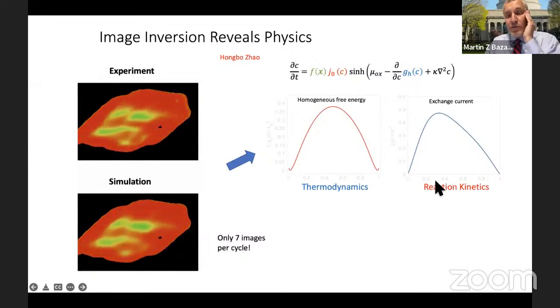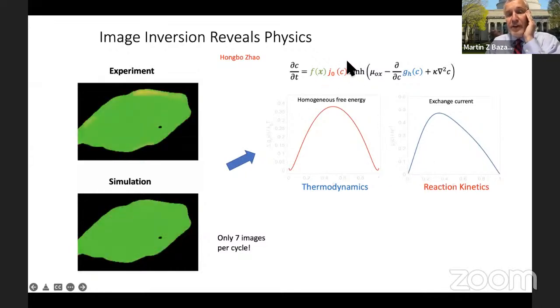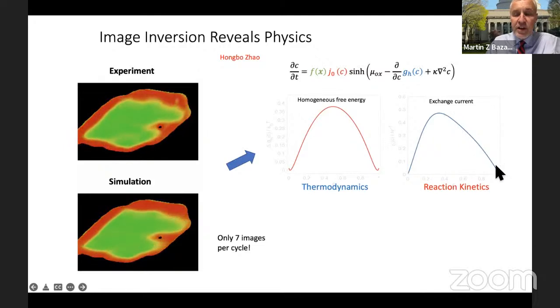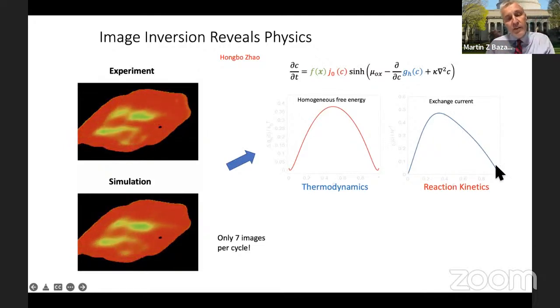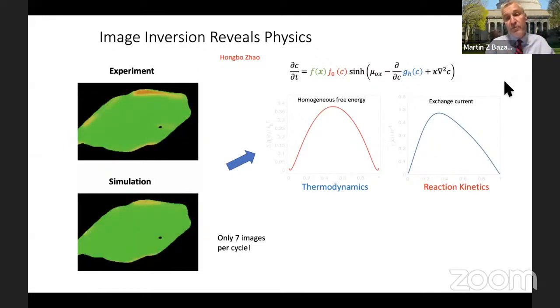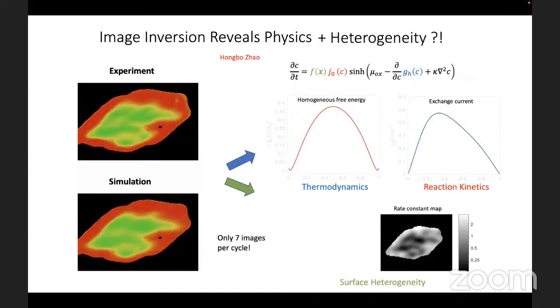We also learned the reaction kinetics. So we learned this prefactor J0(c), the so-called exchange current, which is sort of a decreasing function of concentration at high concentration. So it has that autocatalytic or autoinhibitory behavior that I described before, but it doesn't look like the function that I had written down previously when I first did this work 15 years ago.